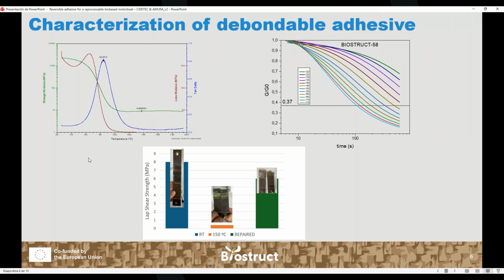And regarding the adhesive properties, we performed a single lap shear test over the substrates manufactured by Amura, and we obtain a lap shear strength of around 8 megapascals at room temperature. And then here we can see that if we heat this adhesive layer up to 150, this shear strength decreases drastically, and we could separate these two substrates by hand, because it has a shear strength lower than 1 megapascal.